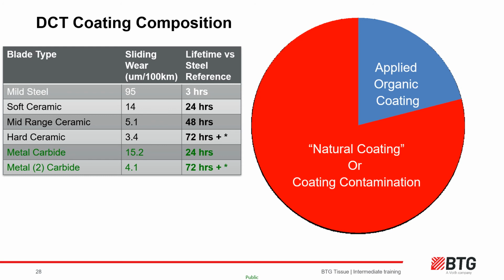Red segment. The red segment is the wet end contamination, or more kindly, natural coating. We have significantly less control over this at the nip than in the wet end and furnish. Natural coating can help coating, especially insoluble hemicellulose from pulps. Even the calcium carbonate from de-ink pulp, from a pH and a chemical perspective, can help coating. However, if the natural coating dominates over the organic coating and increases the cured coating layer significantly, it will eventually lead to hard coating if other conditions align.